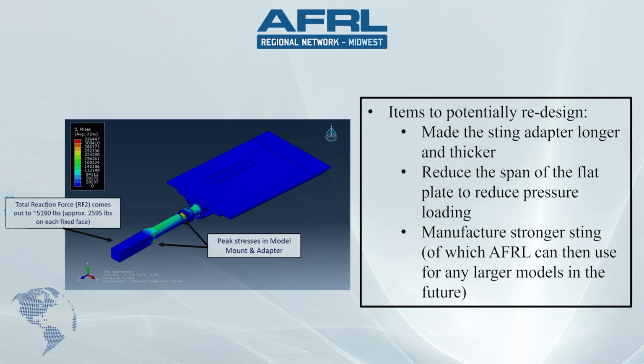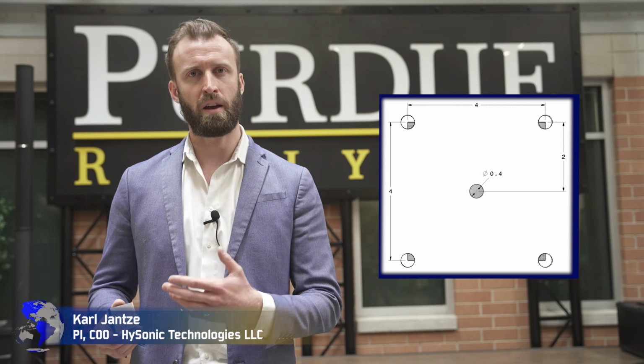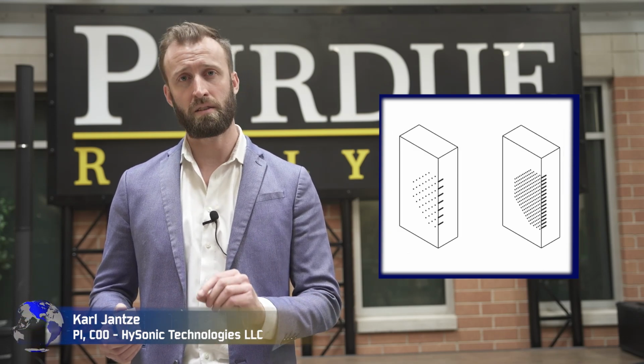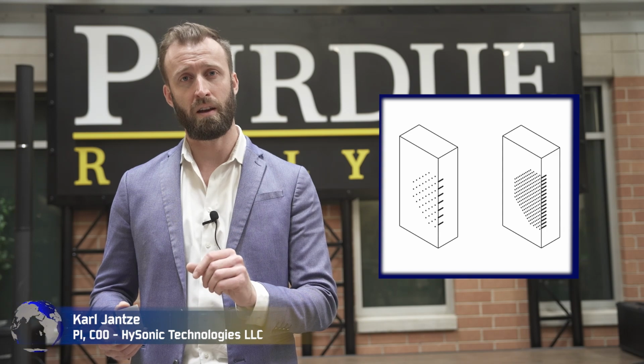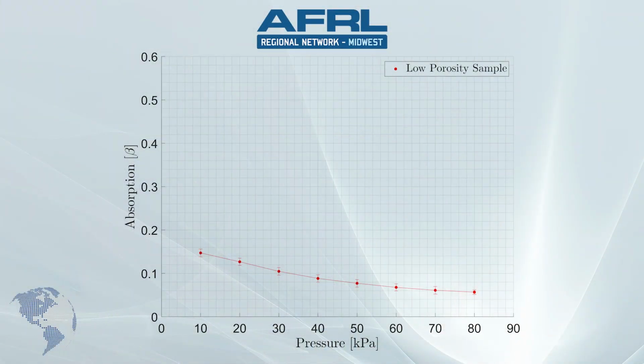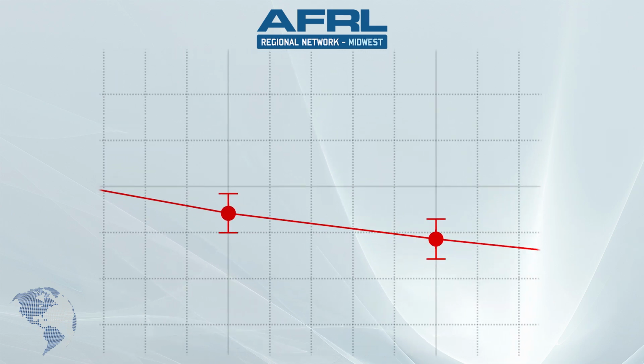In my hand here, we have a low porosity sample. We use stainless steel samples that have cylindrical pores in them with a known depth and diameter used to calibrate and refine our ultrasonic absorption bench test. This low porosity sample has fewer holes than the high porosity sample, but it has the same nominal diameter, depth, and pore diameter. If we take a look at the experimental plot here, you can see the experimental data is given by a red dot that has an error bar. This error bar is calculated by taking this test over and over again and finding out how repeatable these results are, 2 times the standard deviation to be particular.